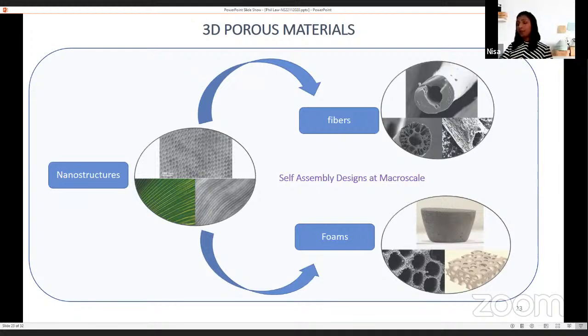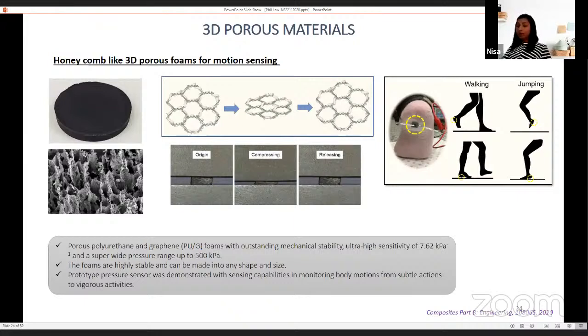We developed functional fibers and foams using this approach. The foams and fibers possess highly ordered, interconnected pores at nanoscale and microscale. We have also demonstrated application of these materials in sensing, energy storage, and absorption applications. Here we combine molecular assembly and also the ordered arrays of structures such as honeycomb-like features in a graphene foam. We made a nanocomposite foam by combining polyurethane with graphene. Addition of graphene leads to the formation of ordered honeycomb-like features.